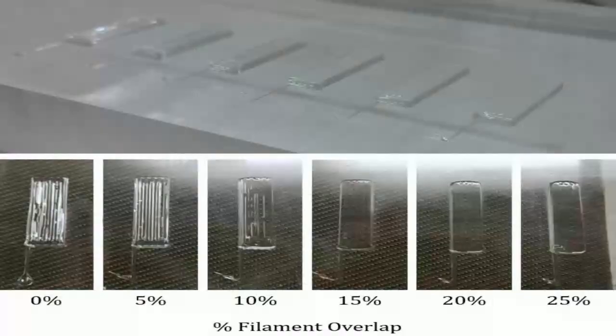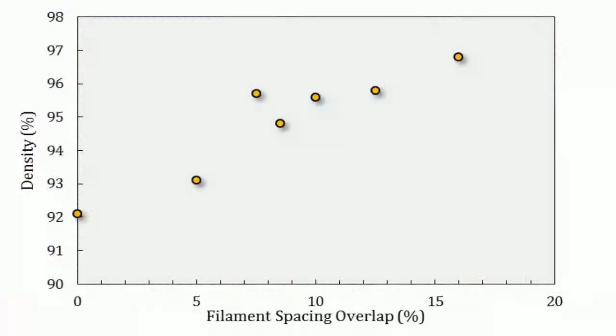More graceful failure. And the layer-by-layer extrusion of robocasting, you said it offers an advantage. Yes, because you can potentially align those reinforcing elements as you print. The shear forces, as the paste gets squeezed through the narrow nozzle, naturally tend to line up elongated particles like fibers or platelets parallel to the flow direction. Ah, like logs floating down a narrow channel. Exactly like that, you get built-in alignment.